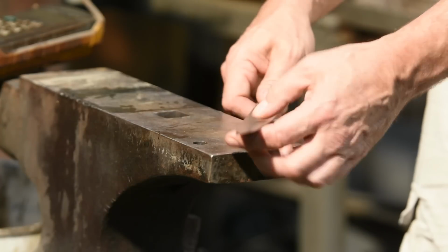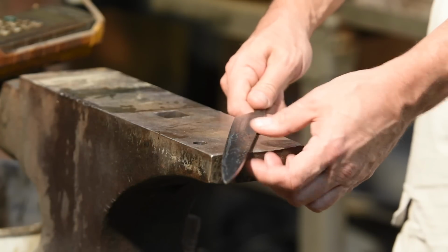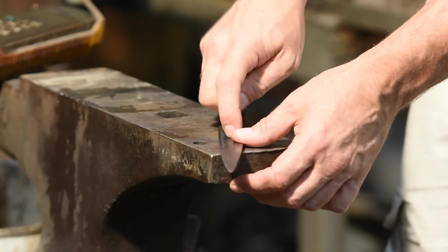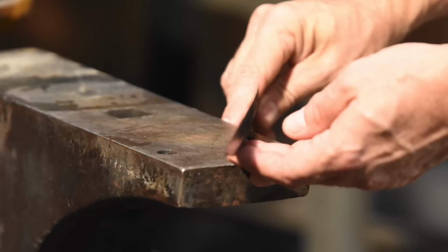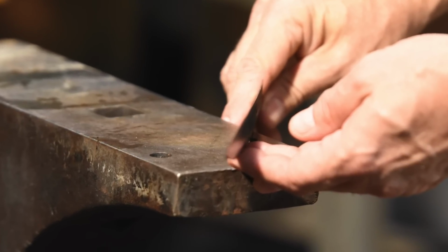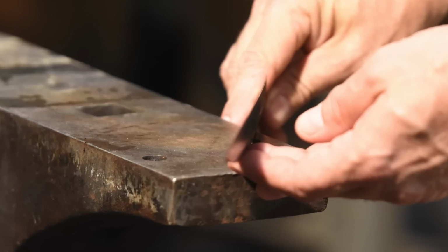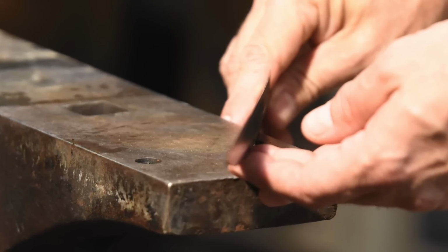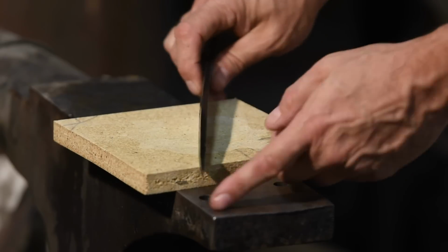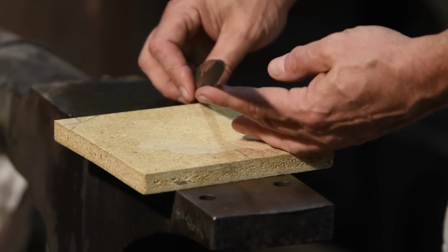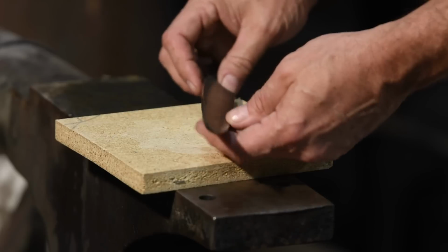Now, martensite, despite the fact that it's harder than other forms of steel, is actually less dense, meaning that it expands slightly when the blade hardens. So that's going to cause the blade to warp. This is really pretty much unavoidable in a two-part laminate like this. So, time for some straightening.